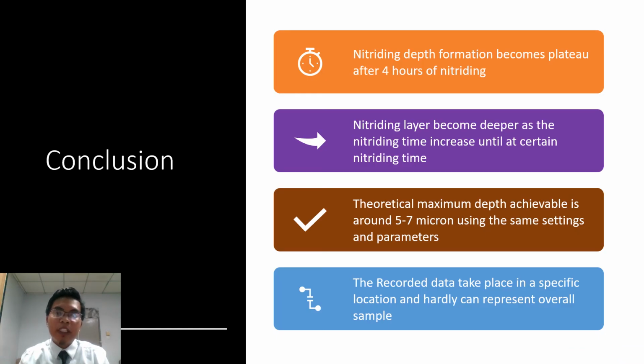So the conclusion from this project is that the nitriding depth formation of magnesium alloy became plateau after 4 hours of nitriding time. The nitrided layer becomes deeper as the nitriding time increases until a certain nitriding time of 8 to 10 hours. The theoretical maximum depth achievable for magnesium alloy is around 5 to 7 micron using the same setting and parameters given in this project. The recorded data was taken at a specific location and can hardly represent the overall sample.